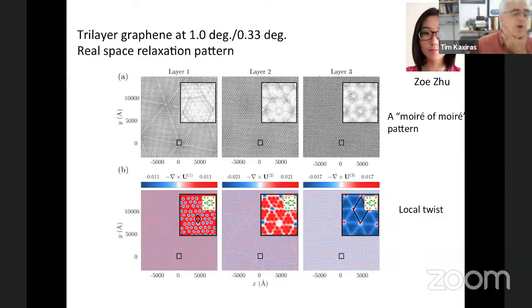So this is a project in which my student Zoe Zhu is concentrating her efforts, and you'll hear from Zoe also a little bit tomorrow. And this is a short overview of the kind of atomic relaxation that you see in this system. And this is what we call a moire of moire. So we don't have just one moire pattern, we have a moire of another moire pattern, and this gives very complicated atomic arrangements, layer 1, layer 2, and layer 3 with blow-ups of the atomic configurations. Again, this is showing the positions of atoms in real space as calculated by the type of calculation that I showed you earlier, and Zoe will elaborate on this tomorrow.